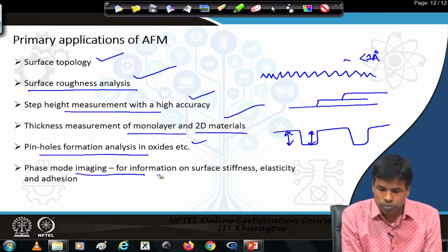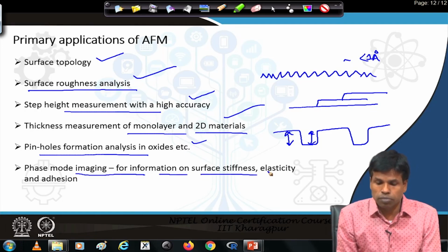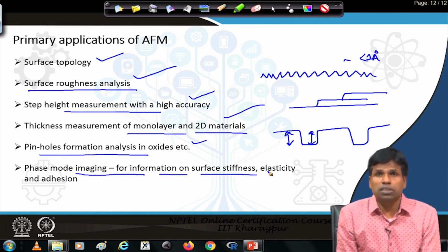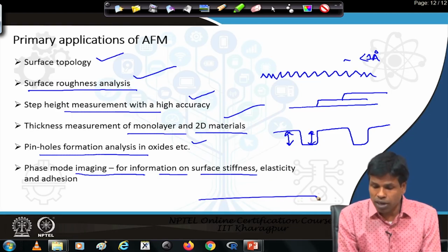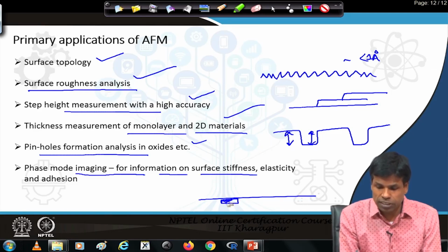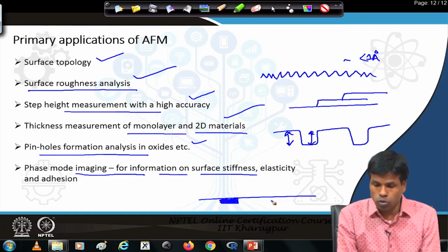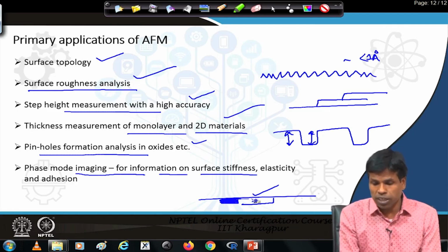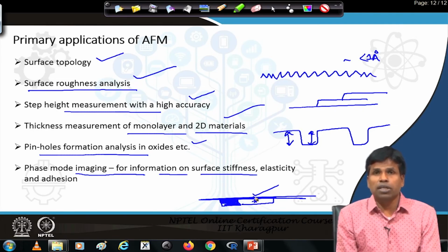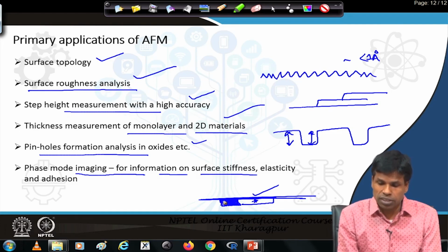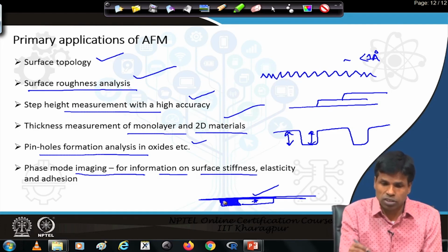Using the phase imaging mode, we can also get information about surface stiffness, elasticity, adhesion, frictional force, all these kinds of study. Like, a sample may be flat, but in some region a different type of material is present; in these cases its adhesion or other properties may be different. This region is different and this region is different. So, even though the surface is at the same height, as the materials are different, they will have different characteristics. So, those things can be measured by atomic force microscope.